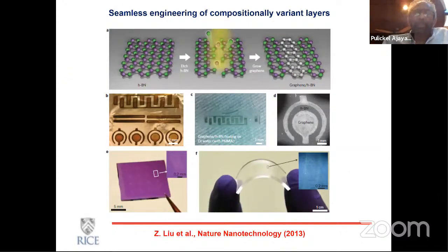And we have been, again, in the recent years, trying to figure out how to control these domain formation, either by growing one layer of one composition, etching it out, and then regrowing in those gaps, and things like that. We were able to create all these beautiful patterns with periodic arrangement of one of those domains. So, for example, you can take graphene and etch parts of it and regrow boron nitride in those gaps. So you get these two-dimensional heterostructure all in plane.